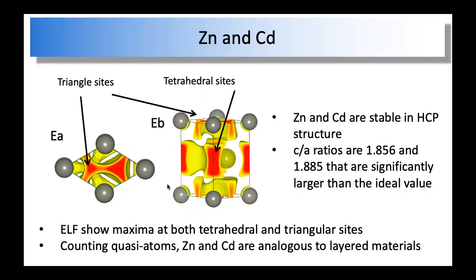However, we still don't understand why the c/a ratio is actually higher there. Well, here is why. Instead of comparing this with alkali metals and early transition metals, the electron localization not only happens at this tetrahedral site, but also at this triangle site. So basically, for zinc and cadmium in this lattice, with this particular lattice length, the electron can also localize at the center of 3 zinc atoms.